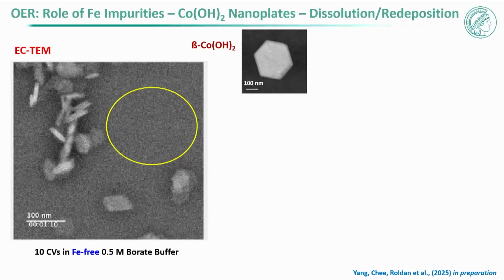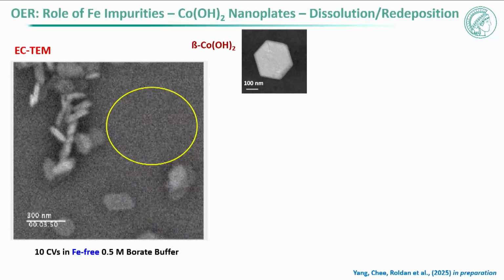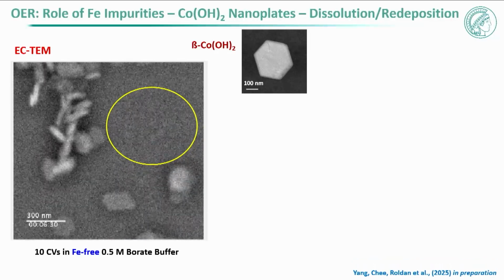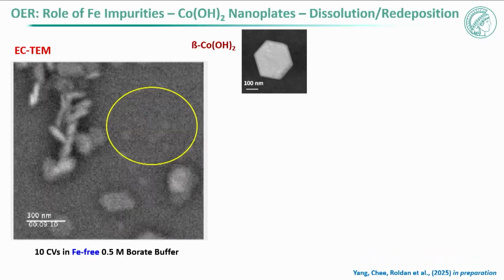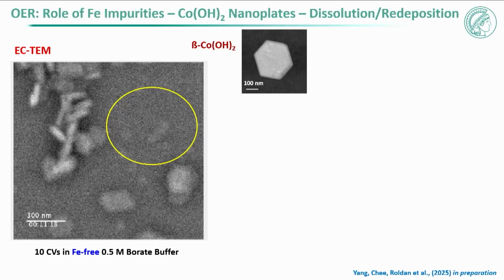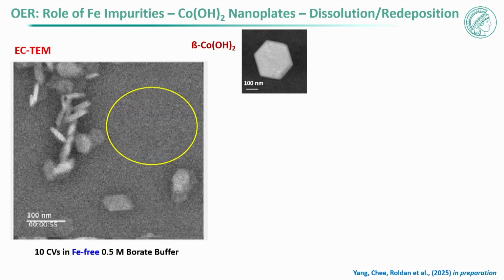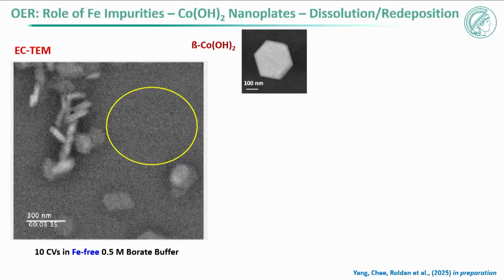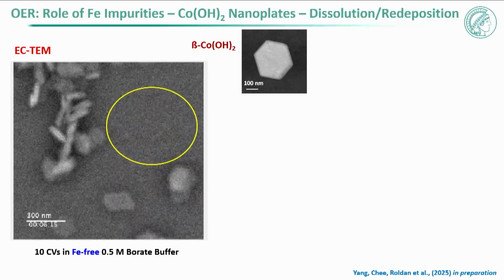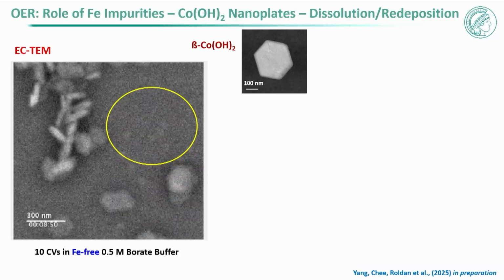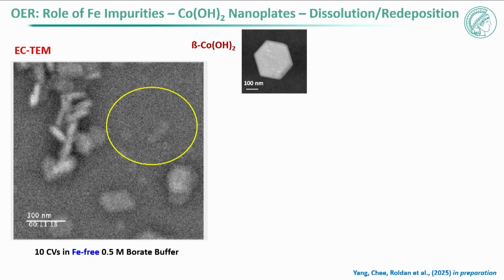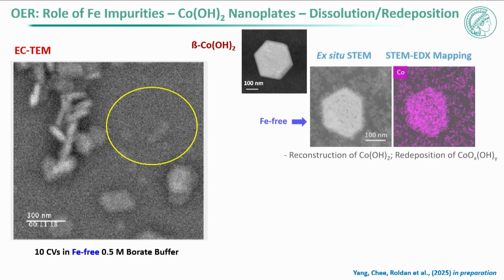I told you these catalysts are not ideal, and one of the problems that we have with these catalysts is that they are changing. If you look at these things here, it's hard to see, but imagine what I'm showing you here. This is a cobalt oxide, in this case, platelets of cobalt hydroxide. This is cobalt hydroxide, and again, we are in a transmission electron microscope. We are under electrochemical conditions, and you see these small things forming here, these small particles. So this comes from the dissolution of our active catalyst.